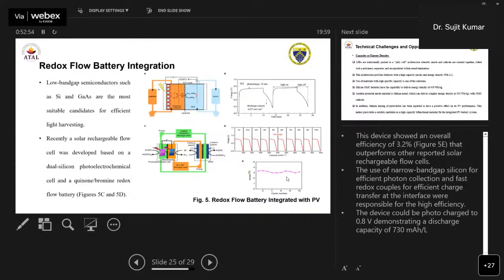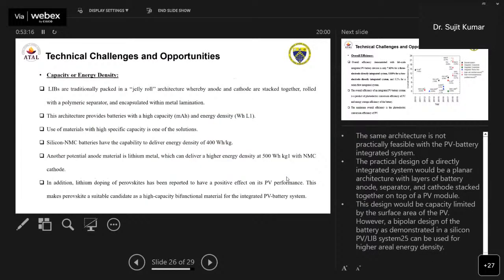So if we use narrow band gap silicon for efficient photon collection and fast redox couples for efficient charge transfer at the interface, they are responsible for the high efficiency. This device can produce a photo charge up to 0.8 volts, demonstrating a discharge capacity of 730 milliampere hours per liter. Okay. So these were the overall recent trends, where the efficiencies, compared to conventional batteries with separate photovoltaic cells, are being improved with the help of integrated designs, where we have seen direct integration, photo assisted integrations, and redox flow couples.